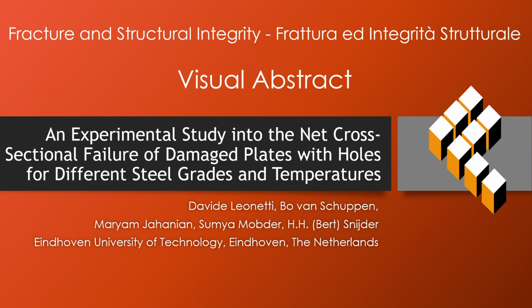In this work, we report an experimental study into the net cross-sectional failure of plates containing holes which are pre-cracked. The study is conducted for different steel grades and temperatures.